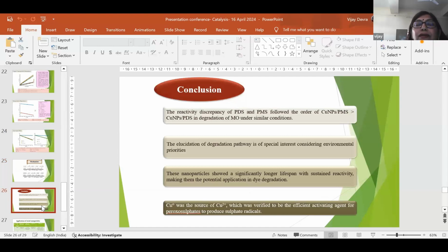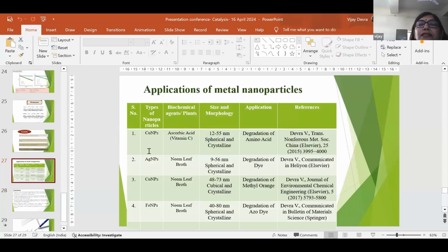And now, the time of the conclusion. The reactivity discrepancy of peroxodisulfate and peroxomonosulfate followed the order: copper in the presence of peroxomonosulfate is greater than in the presence of peroxodisulfate in the degradation of methyl orange under similar conditions. And the elucidation of the degradation pathway is of special interest considering environmental priorities. These nanoparticles showed a significantly longer lifespan with sustained reactivity, making them potentially applicable in dye degradation. There are many more applications in the presence of metal nanoparticles. This is my study.